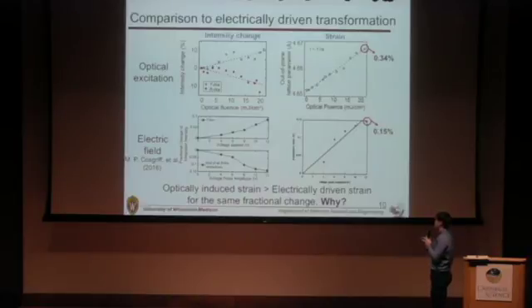But the thing is, electrically driven phase transition shows this 10% change with 0.15% strain, which is much less than what we have observed in the optical excitations. So we have seen 0.34% strain for the 10% intensity change. If the converse piezoelectric response is the source of this phase transition, we think this strain should be the same. So we set up the hypothesis that the additional lattice expansion arises from the thermalization process.